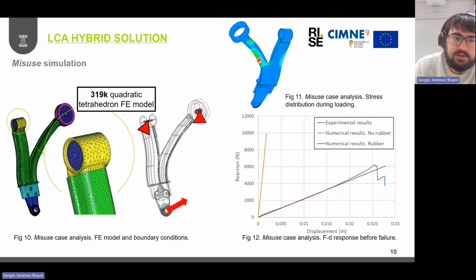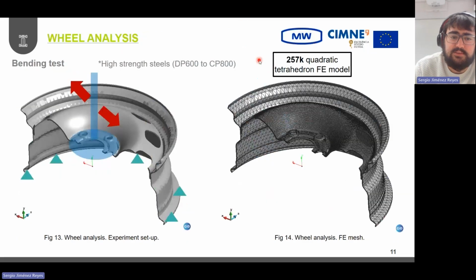But now let's move towards the two other demonstrators that have not been presented previously. The first one is this wheel here, where we applied this conventional bending test. So this is the type of experiment that the experimental partner, in this case Magneto Wheels, is performing for their wheels in order to check the fatigue response of the wheel itself.